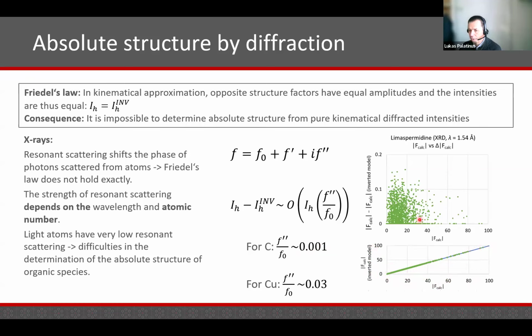Only if we calculate the differences between the calculated structure factors of the two enantiomorphs, so the two absolute structures, only here we see very small differences, again of the order of 0.1% or so. So it is possible to determine absolute structure with X-rays, but it is difficult and you need really good data, especially for all light atom structures.